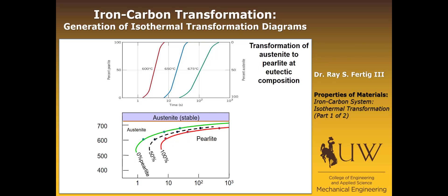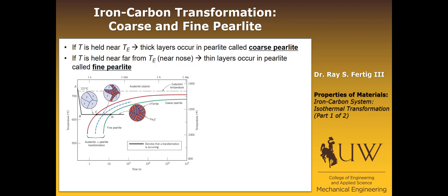We can label each of these curves as where we have 0% pearlite, 50% pearlite, and 100% pearlite. Anything to the left of the green curve is austenite, and anything to the right is pearlite. This diagram is what we call an isothermal transformation diagram, or time-temperature transformation diagram — sometimes just called a TTT diagram. If temperature is held close to the eutectoid temperature, we have relatively slow nucleation and relatively fast growth, producing large structures with thick layers — what we call coarse pearlite.